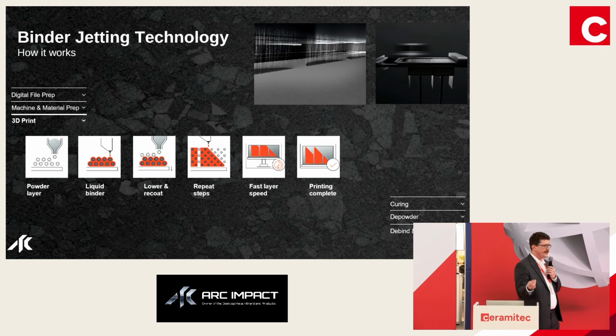So if you're not familiar with binder jetting technology, as I mentioned, it's a powder bed-based additive technique where you start with a digital file of some sort, a step file, an STL, some model of your desired geometry. We load that into the machine software. We do some slicing of that geometry to build layer by layer. We prep the machine itself with the powders and the binders that we want to use. We set up the printing parameters that we want to use, and then we hit go.